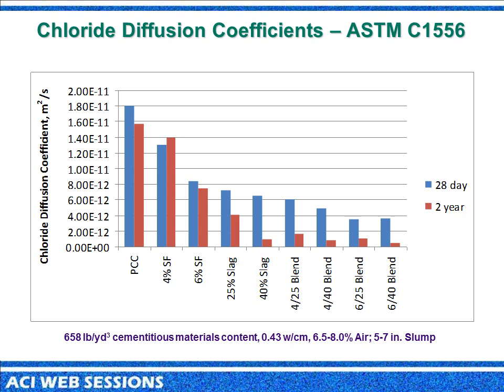So when we look at the chloride ion again, we can see very good performance from 25% slag and very good performance from 40%. And then we also see the blends which come down here at a very, very low level. Now, economically, we also see benefit here. Economically, slag cement is traditionally less expensive than your traditional Portland cement in some markets. It varies across North America. But certainly we could see more economical aspects versus a straight Portland cement mixture.